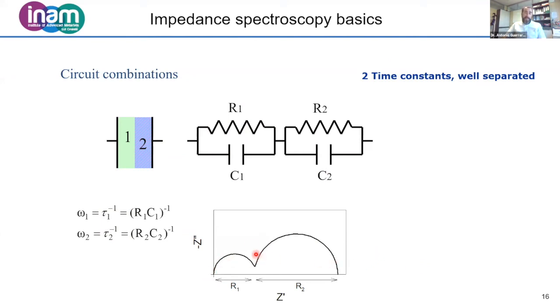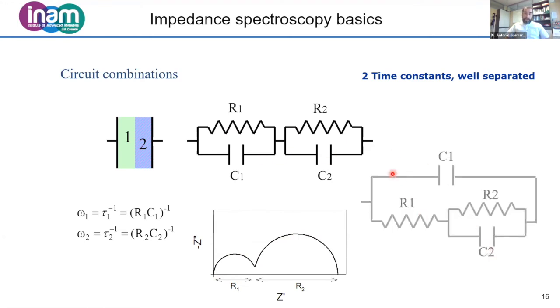So usually the different processes are coupled, because electronic processes usually happen on the same time scale. This would be different, for example, if we compare electronic processes with ionic processes. Ionic processes are typically slower. They could show at lower frequencies, and in that case, maybe it's possible to see two well-separated arcs, but that depends on the material. So one needs to be aware that there are different equivalent circuits that would fit the experimental data.